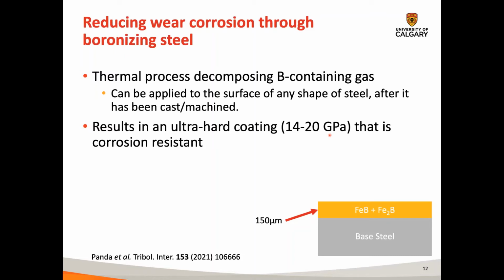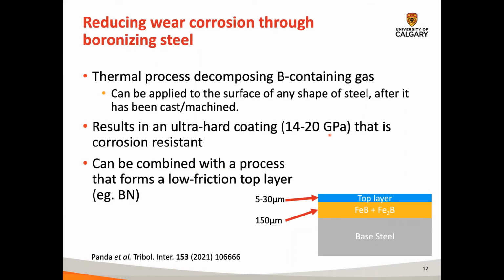And I think when I saw a talk from them, they said that the resistance is like a factor of 20 improvement in the lifetime of the pieces. They're looking at new processes where they can also put low friction or dry lubricants on top of the boronized steel. For example, boron nitride, and they play with the chemistry of the boron nitride a little bit so that the friction is even more reduced, and so these particles can slide off even easier.